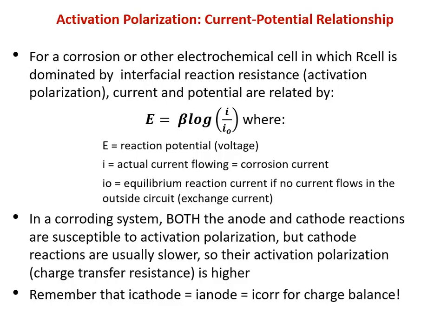It's called the exchange current density, and it's basically the current that would be flowing if we weren't driving the system from the outside, kind of like a little dynamic equilibrium with no net current flowing through the external circuit. So this is another log relationship, and it's frequently referred to as the Butler-Volmer equation, and it just describes the chemical kinetics. But it's a resistor, if you want to think about it, that does not follow Ohm's law. So you can see in Ohm's law we have a linear relationship between current and potential, and here we don't.